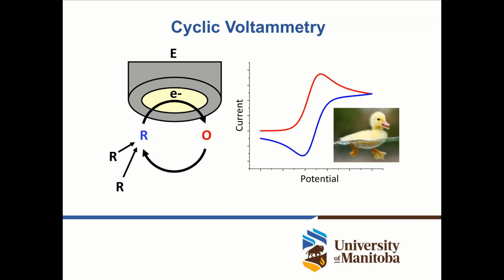When we plot the data that we receive from this, we plot it as a current potential plot that, when we sweep the voltage forward and backwards, oftentimes resembles the shape of a duck, if the reaction is chemically reversible. So here in this figure, you see in red an oxidation peak and in blue a reduction peak, if the reaction is chemically reversible.